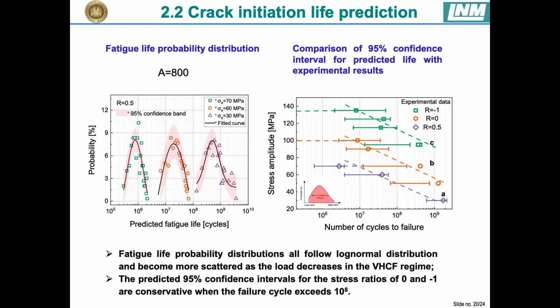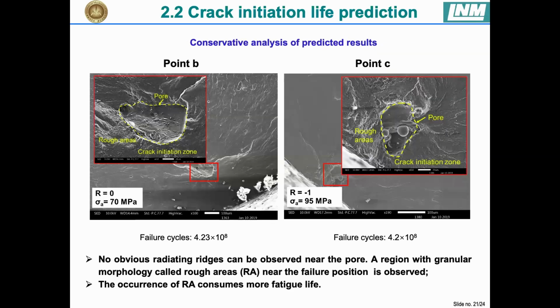And it also becomes more scattered as the load decreases in the very high cycle regime. Then the comparison of 95% confidence intervals for the fatigue life probability distributions with the experimental results shows the predicted 95% confidence intervals for the stress ratios of 0 and -1 are conservative when the failure cycles exceed 100 million cycles.